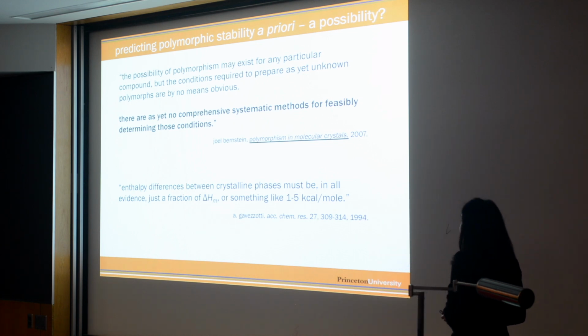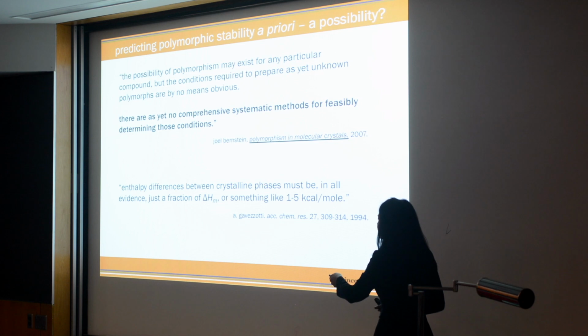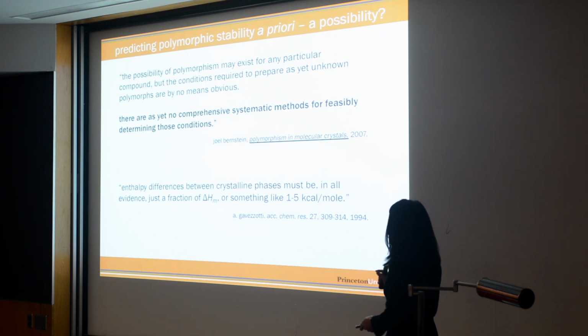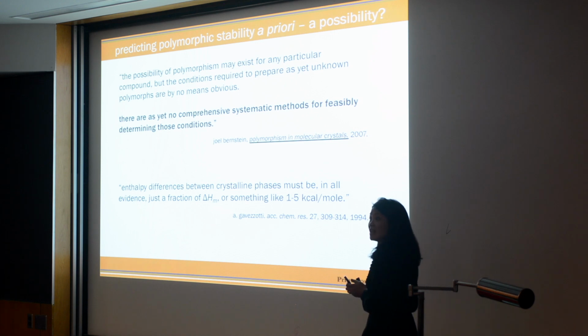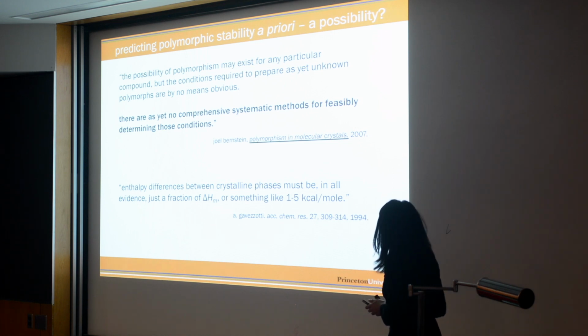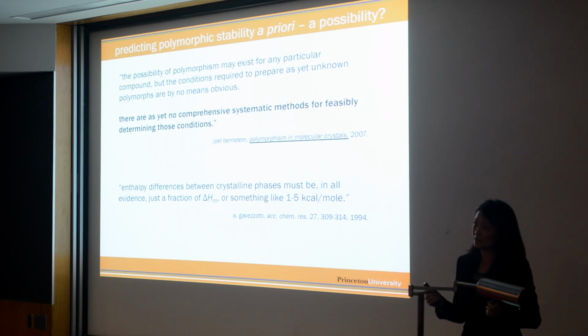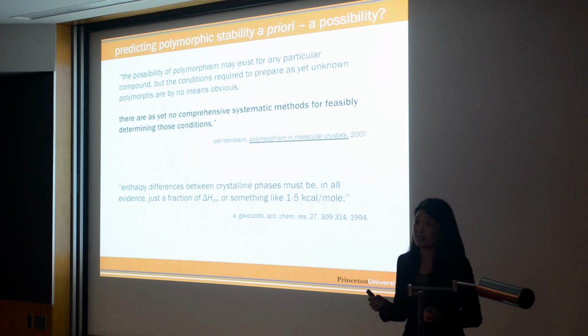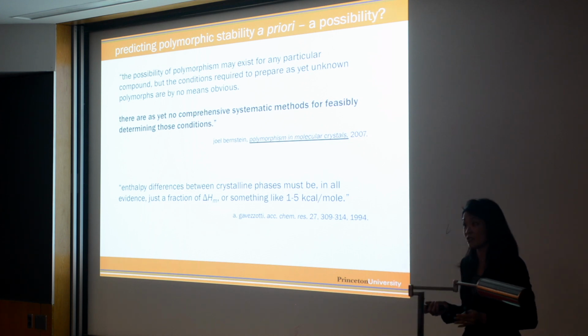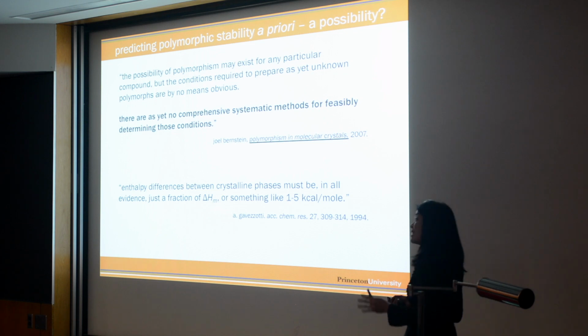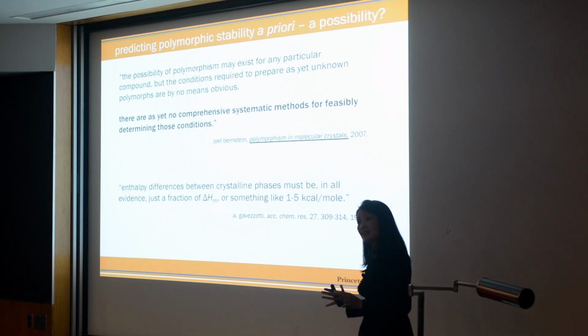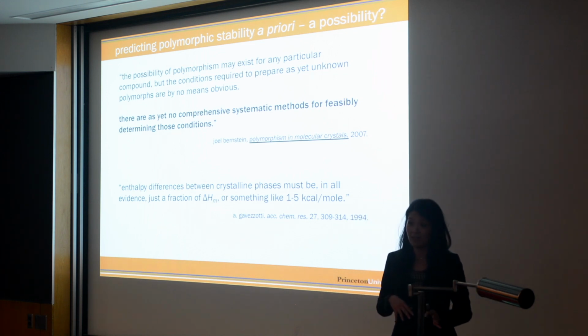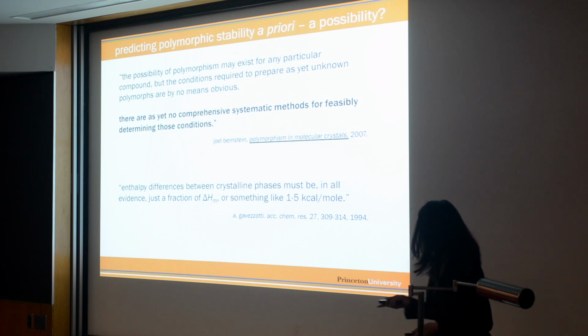So complicating this situation is the fact that these enthalpic differences between these different polymorphs are very small. They're only a small fraction of your delta H, the melting delta H. So for all practical purposes, I'm going to refer to these polymorphs as being practically isoenergetic. And so it's really the kinetic constraints that then dictate which polymorph you access and which ones are kinetically stable.